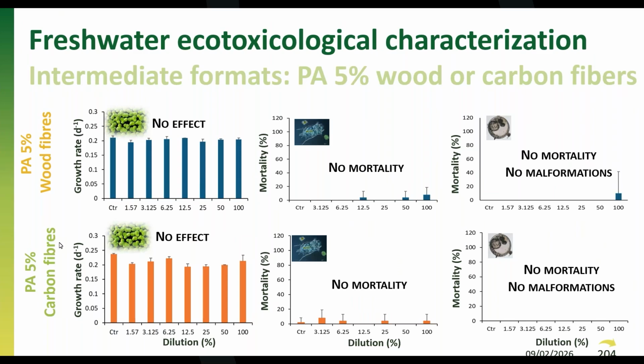meaning no effect. And then for the rotifers and for the fish, we also had no effects of any of these intermediate formats. So it is interesting to understand that even though we observed some toxicity of the fibers alone, when they are incorporated in these intermediate formats, the elements that can induce that toxicity are not leached into the aqueous medium, so turning it safer. Next slide, please.